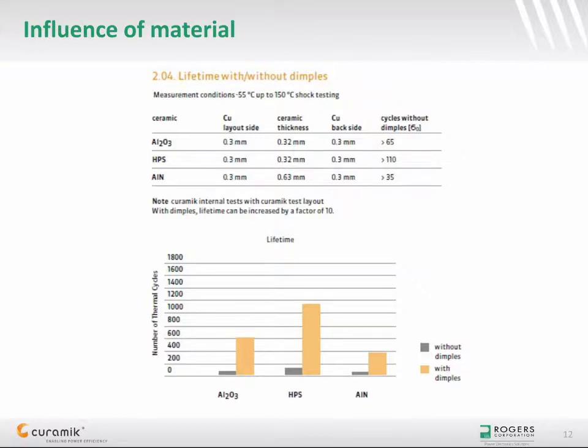The lifetime of substrates also depends on the thickness ratio between copper and ceramic. Generally speaking, a thick and strong ceramic substrate, metallized with a thin copper layer, is expected to withstand much more cycles than a thin and fragile ceramic substrate with a thick copper metallization. Those thicknesses are usually designed to achieve the required insulation, heat dissipation, and current density, but you should be aware that the best electrical and thermal design is not likely to be the most reliable. A trade-off will be required, and this trade-off may not always be the same for the different applications, as requirements and mission profiles are likely to vary. The main concern with material selection is that it often has a cost impact, and it is not surprising that the most reliable materials are not the cheapest materials.